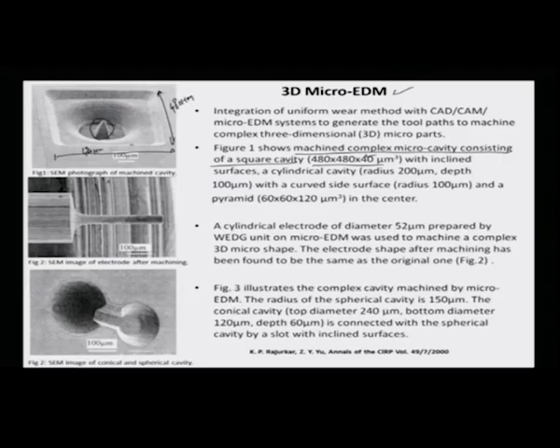The radius of this cylindrical cavity is about 200 microns, and the depth of this cavity is about 100 microns. And if you look at the pyramid structure, the pyramid is about 120 micron tall, and it's a square pyramid. So, each side of the square is about 60 microns by 60 microns. This speaks highly of the process capability of EDM to do 3D micro structured architectures or parts.